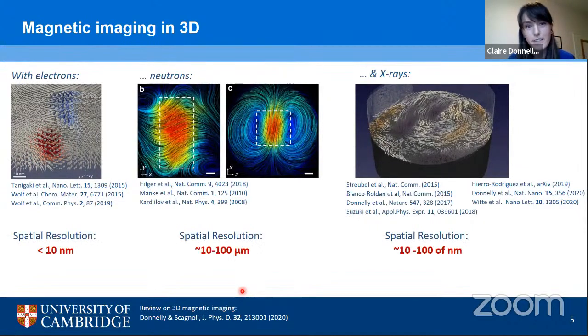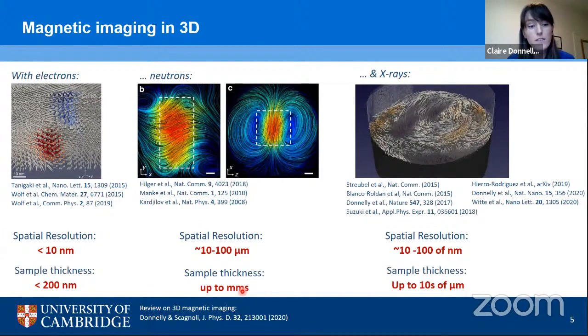We first of all need to consider the spatial resolution. So what is the smallest structure that we can resolve with these techniques? Secondly, we need to consider what is the thickest sample that we can look at. So how deep within a material can we penetrate? And if we compare these different probes with electrons, we have very high spatial resolution. So that's perfect for the study of topological magnetic structures. However, we are limited to sample thicknesses of about a few hundred nanometers.